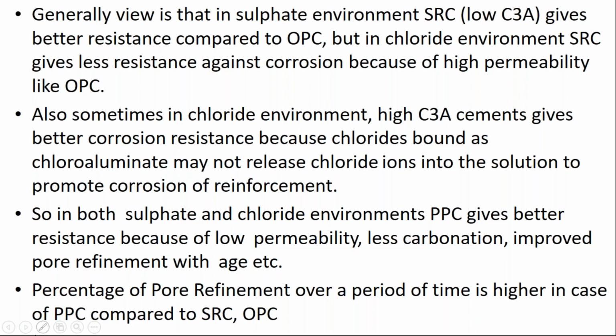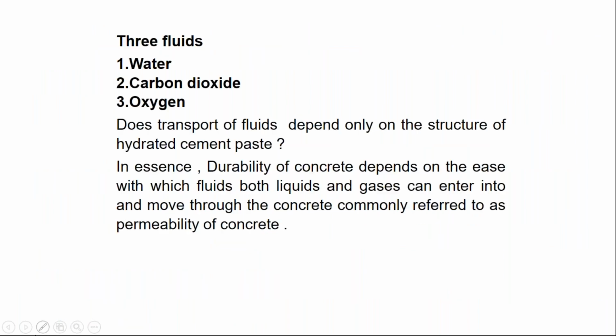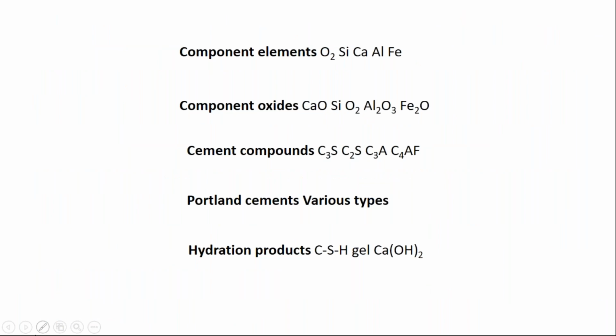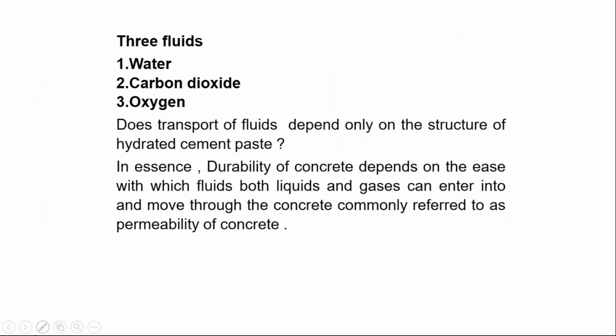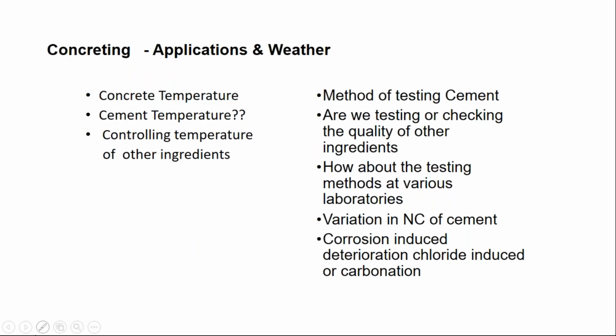And even the ultimate strength over a period of time, the concrete gains strength, because basically it is a blended cement. So this is the fundamental on which the durability of concrete is based, because the ability of the three fluids, carbon dioxide, we talk about carbonation, oxygen, and water, to get into the concrete is what determines the degree of durability of concrete structures.